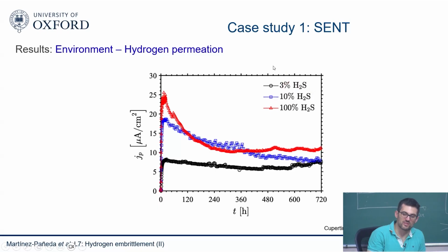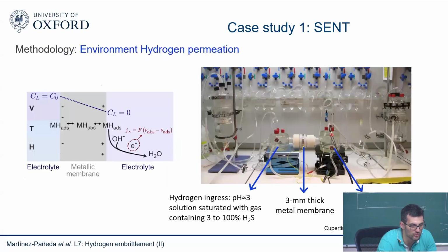So the problem is that H2S is a poison. It's a combination poison, so it means that you get much more hydrogen into your metal than we normally would, because it slows down the recombination reaction. Remember I mentioned that hydrogen actually doesn't want to enter your metal. Hydrogen wants to go away from your metal. So hydrogen would like to recombine into a molecule and then just leave.